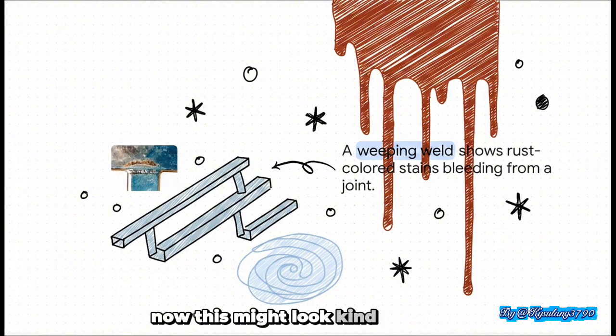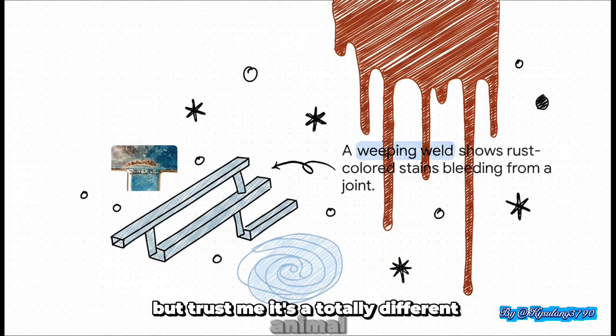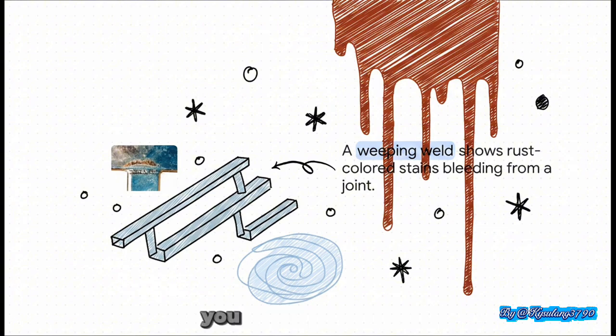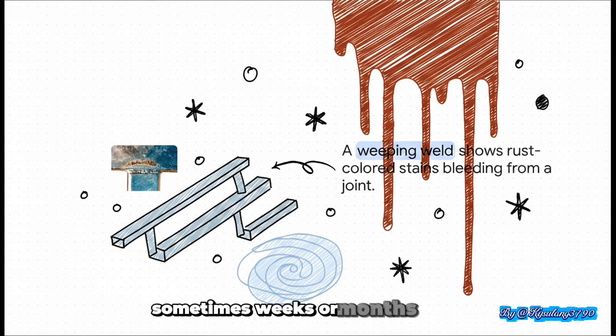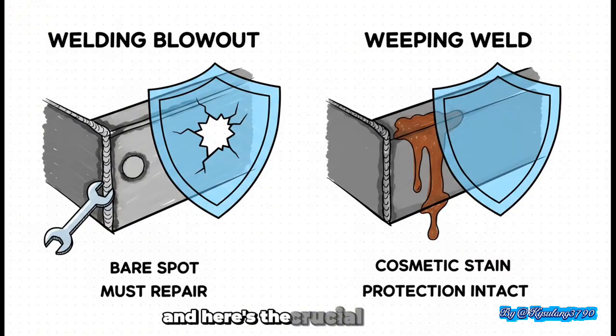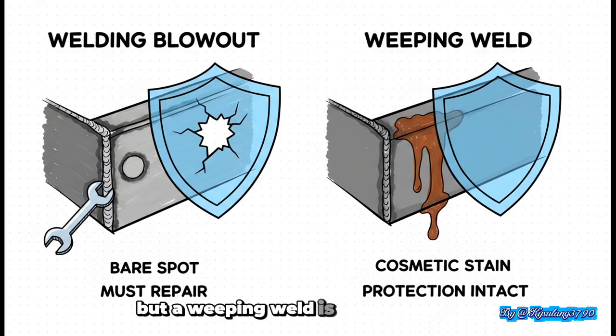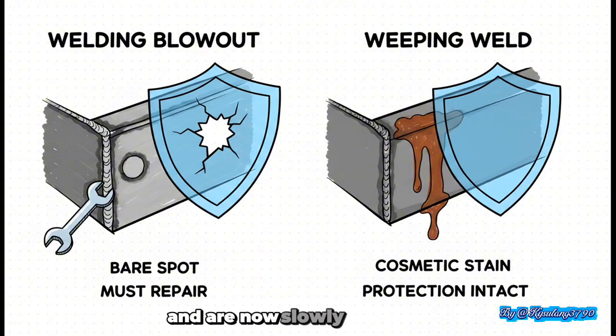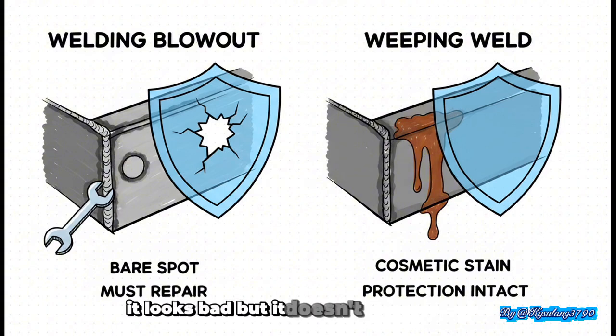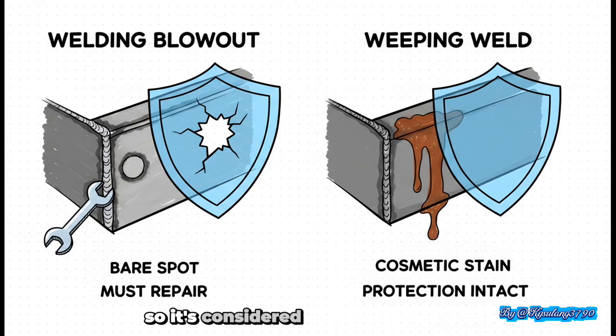Now, this might look kind of similar, but trust me, it's a totally different animal. This is called a weeping weld. You get these ugly rust-colored stains that seem to bleed out of the joint, sometimes weeks or months after galvanizing. And here's the crucial difference. A blowout leaves bare steel, which means no corrosion protection. That's a defect the galvanizer has to fix. But a weeping weld is just a cosmetic stain. It's caused by cleaning fluids that were trapped and are now slowly leaking out. It looks bad, but it doesn't actually harm the coating. So it's considered a fabrication issue, not the galvanizer's problem.